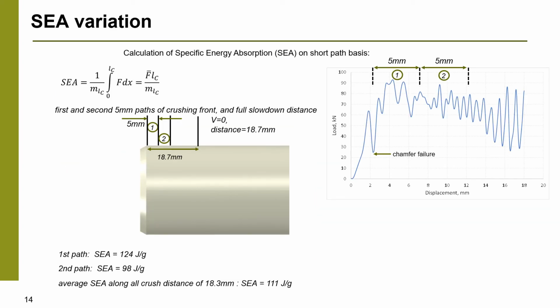On the slide you can find the load versus displacement diagram during the crash process. At the initial stage you can see a sudden drop of the reaction force caused by chamfer failure, and then the stable crash process begins, and we calculate the specific energy absorption characteristic for the first 5 millimeters of the stable crash path and for the second. So if we compare, we can find that on the first pass it is significantly higher than on the second pass.